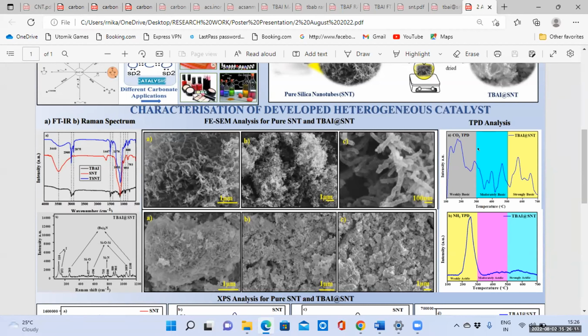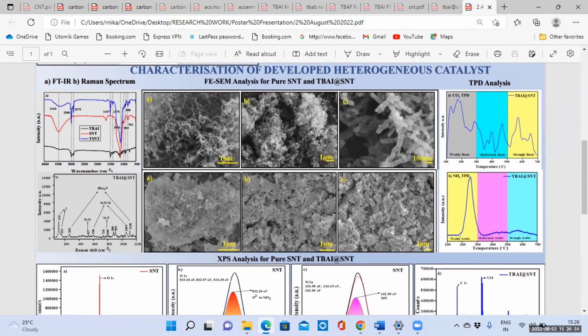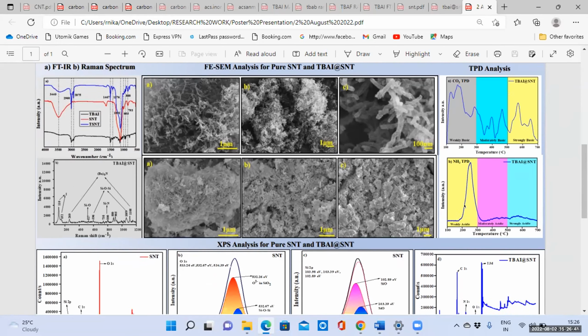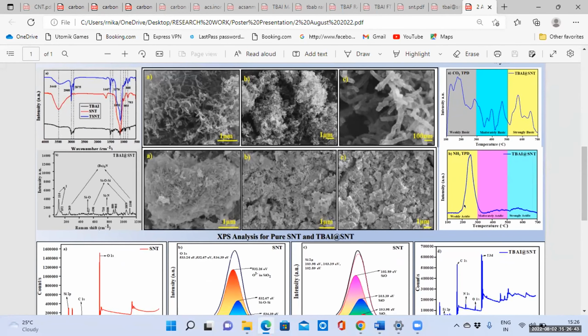The white shiny particles on the tubular morphology were obtained due to the grafting of TBAI on pure SNT. Further, to study the characteristics of acidic sites and basic sites, TPD analysis was carried out. CO2 TPD analysis was carried out to study the basic properties of the synthesized catalyst, and ammonia TPD was carried out to study the acidic property of the synthesized catalyst. In case of CO2 TPD, the amount of basic site was found to be 0.0191 millimole per gram. And in case of ammonia TPD, it was found to be 1.2211 millimole per gram.